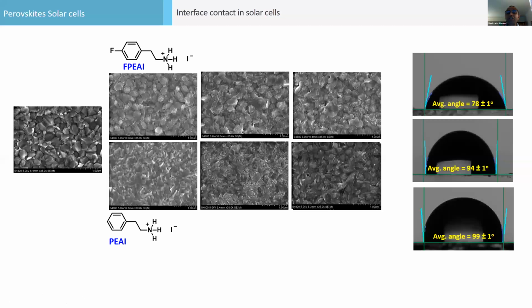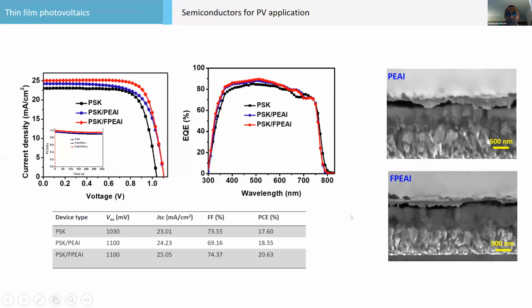So this ultra hydrophobicity induced in the bilayer perovskite will allow us to make the device more stable. I think many people have published extensively on this one. Even they do 1,000 hours of MPP tracking, as has been reported. In our case, we also improved the efficiency: the pristine perovskite gives you 17.6%, but this bilayer perovskite is close to 20.6%, or close to 21% efficiency. If we look at this JV curve, this red curve is the fluorinated molecule, followed by a blue curve, ethyl ammonium iodide, and the pristine is here.